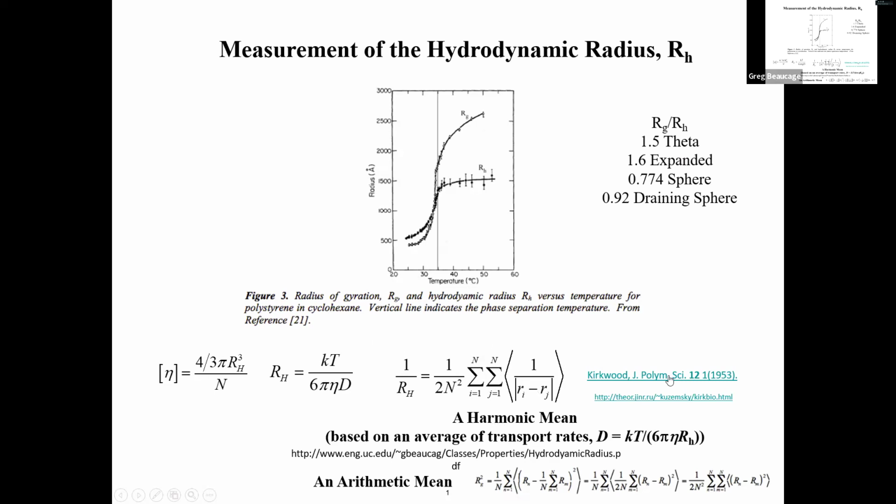If you look at this paper or you look at the equations, they're really complicated. Right. It's not that easy to do this. And this is also assuming that you have no solvent stuck to the polymer. So a big part of this is draining, the draining of the polymer coil. If the coil is sitting there and all the solvent within it is enclosed, and then it acts as a sphere, that's called the Zimm limit for the viscosity.